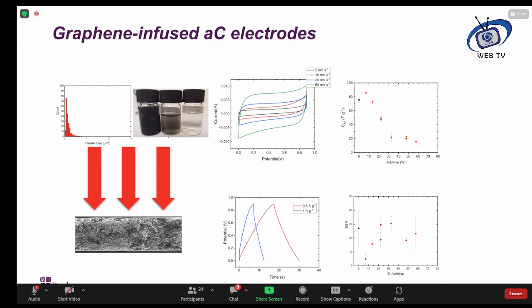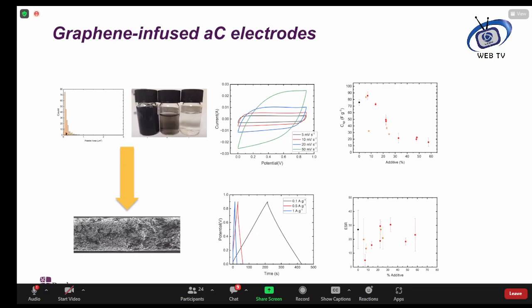So one thing we thought was perhaps that we were having a size distribution that was too large, and that we could improve performance by having smaller graphene platelets that would infuse better within the electrode, make better links between the activated carbon particles, and assemble less at the surface. In fact, the opposite was true. So we've got here a narrower distribution, of smaller platelet sizes that we've infused in the same way, and you can see that the cyclic voltammograms are considerably less rectangular, and there's more curvature to the galvanostatic charging and discharging curves. And if we look at the amber-coloured squares on the plots for specific capacitance and for effective series resistance, you can see that generally there is a worse performance.